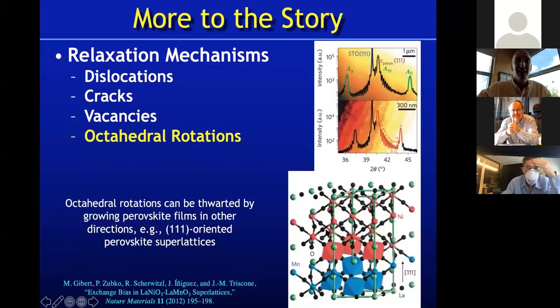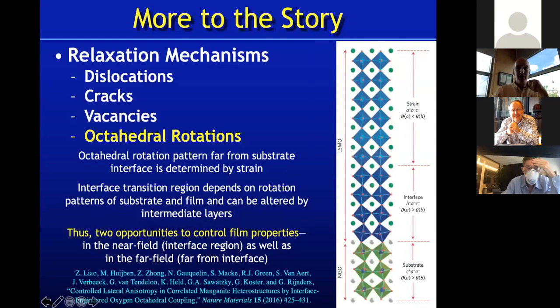Okay, so the last thing I want to say about the octahedral rotation issue is that everything I've been talking about up to now has been with 100 as the growth direction of the perovskite. And with 100, go back a second, the connection between the substrate and the octahedra is just at a single vertex. So it's at a point. And you can imagine, having rotations and rotations that damp and fall off as you go further away from that point.